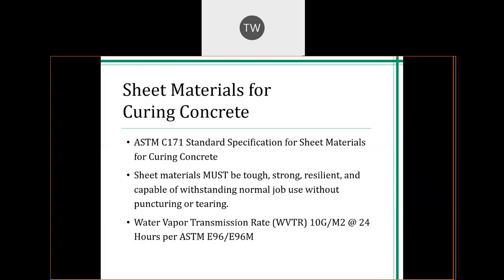Now let's take a step back and talk about some of the methods we have learned for curing and discuss how they are specified. Remember that if we don't specify the external curing method properly, we may be left with a less than desirable piece of concrete at the end of the day. As we had discussed earlier, if you're going to go with a sheet material and would like to specify that, ASTM C171 will help by ensuring the material specified will work for externally curing concrete. This is going to have a low water vapor transmission rate, and you're going to have no more than 10 grams per square meter at 24 hours, as described by ASTM C171 specification.